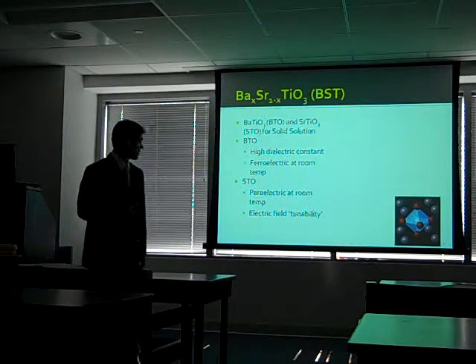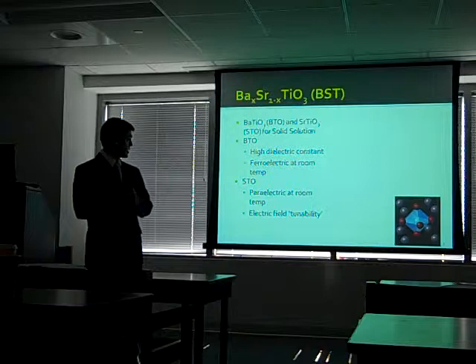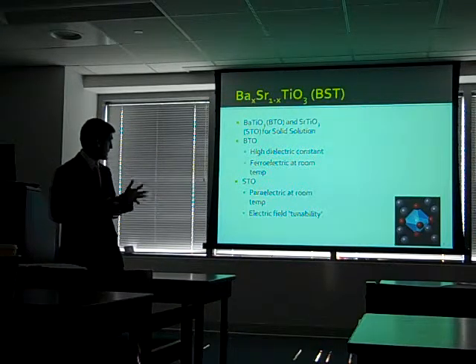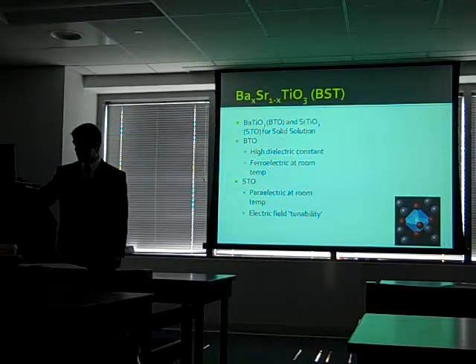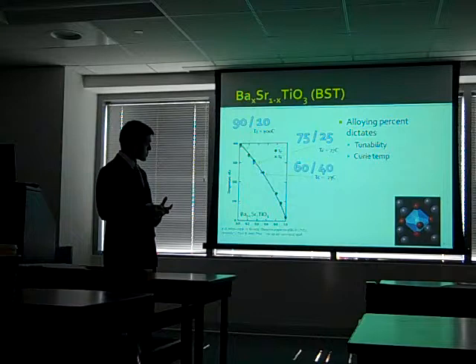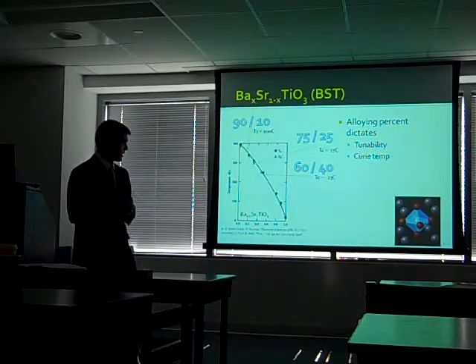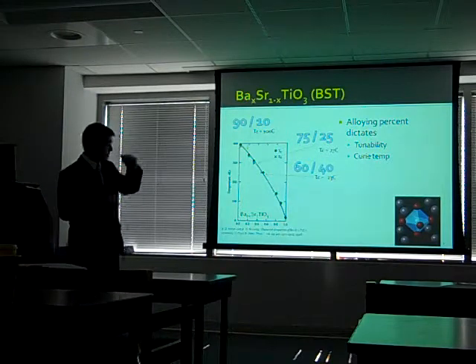Barium titanate is known for its high dielectric constant, as well as it being ferroelectric up to 100 degrees C. Strontium titanate is paraelectric, and like barium titanate, is known for its strong electric field tunability. So by alloying them together, one gains control over the Curie temperature of the alloy as well as the tunability. And then again, we can use this and make a compositionally graded multilayer structure, to get these properties that we're talking